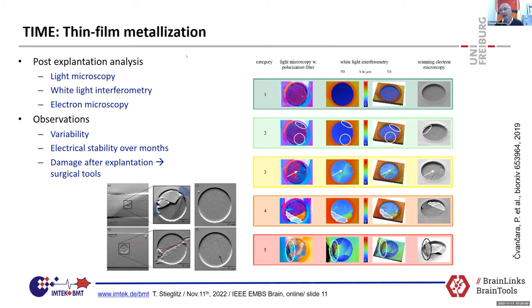And we found out that a lot of those electrodes, category 1 and 2, were still working well, which was in accordance with those 80% perception rate after 22 weeks. And this is something which I believe is very important to get the idea of how we can do condition monitoring of the electrodes. Do we know how they work and what the failure modes are? We've seen some indications that there might be stress cracking on the electrodes, but we still have to work on that in further studies to really find out what the body does with the implants, since they stayed stable for similar conditions in vitro up to 5 billion pulses.